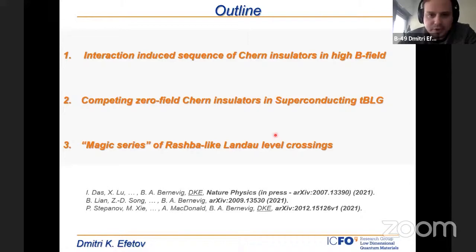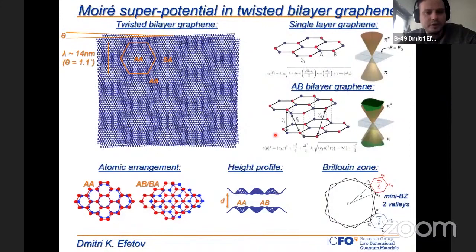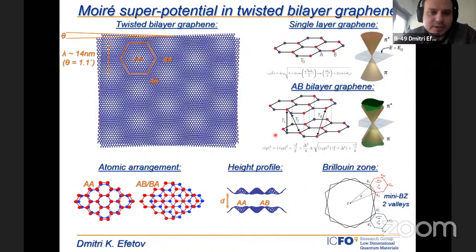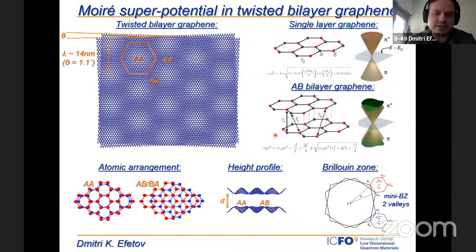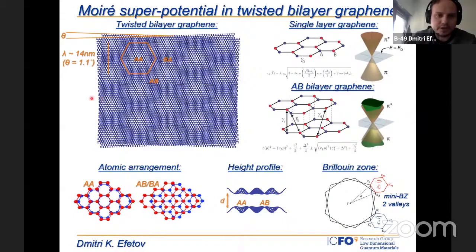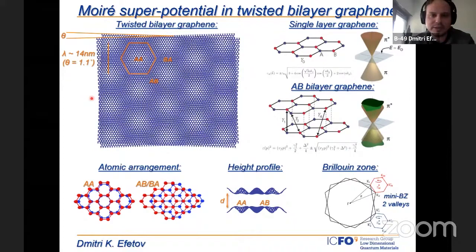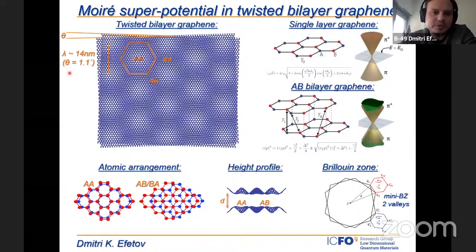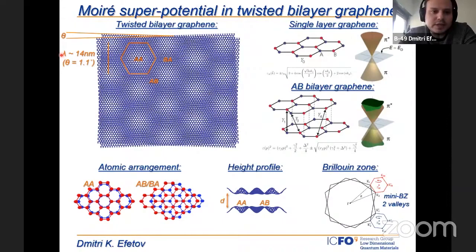Just a very brief introduction to Twisted Bilayer Graphene. The system consists of two sheets of graphene which are basically stacked one on top of another. A simple geometric interference between the lattices of the top and bottom graphene layers gives you a so-called Moiré superlattice. For the twist angles of interest — usually very low twist angles around 1.1 degrees, the magic angle — they have really long periodicities. The lattice constant of the Moiré lattice is really on the order of 14 nanometers, almost two orders of magnitude bigger than a typical carbon lattice spacing.